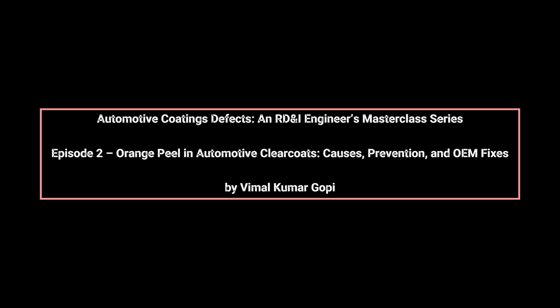First, verify that the correct solvent blend is used for the current temperature, humidity, and film thickness. Second, confirm that flash-off times match TDS recommendations, with adjustments for environmental conditions. Third, measure wet film viscosity and ensure it aligns with process specifications. Fourth, check spray equipment parameters, including air pressure, nozzle selection, and gun movement. Only after these primary levers are optimized should flow and leveling additives be considered for fine-tuning.